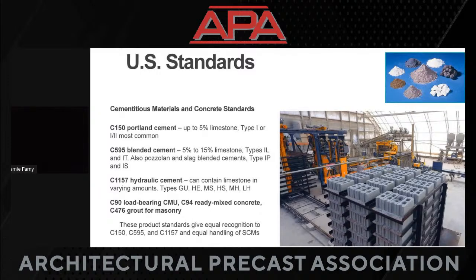So we've got that C150 Portland cement standard that's been around for a very long time. It allows up to 5% limestone, for almost 20 years here in the US now. Type 1 or a type 1-2 is going to be the most common. So what we're talking about is a material that can perform a lot like that, but it comes under a different standard, the C595 blended cement standard, also from ASTM. It shows you that 5 to 15% limestone limit.